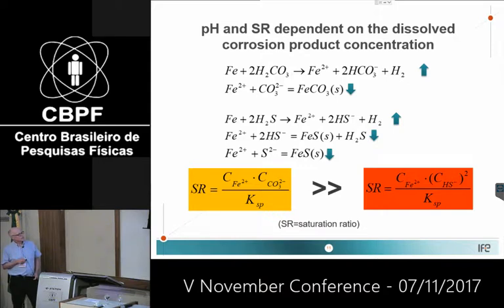Usually, SR is the saturation ratio. If the saturation ratio is 1, you have just reached the saturation level. But you can have a supersaturated system. And for iron carbonate, you usually have a huge supersaturation, but not for iron sulfide. So while you can have supersaturation 1,000 times in a CO2 environment, it can just be close to 1 when you have H2S present.